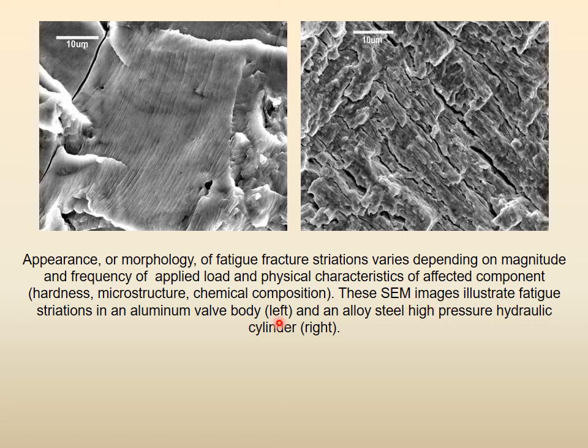These SEM images illustrate fatigue striations in an aluminum valve body on the left and an alloy steel high pressure hydraulic cylinder on the right. So this was the aluminum and this was the steel, and roughly the magnification, if you see, this is 10 microns, this is 10 microns, so they are roughly at the same magnification. So you can see that if you are experienced, then even though there are striations here and striations here, just by looking at the difference, you would know this is some type of aluminum alloy and this is some type of steel alloy and so on, right? So if we work in a particular environment in the industry or in the research labs, then we get used to it very quickly. So you see the beautiful striation marks under fatigue failure.